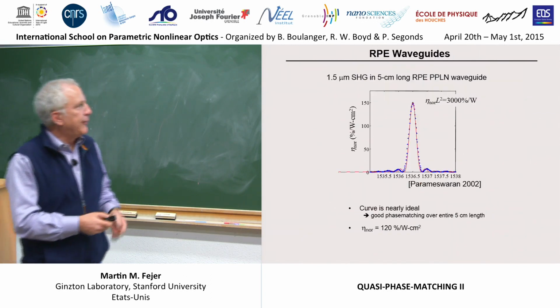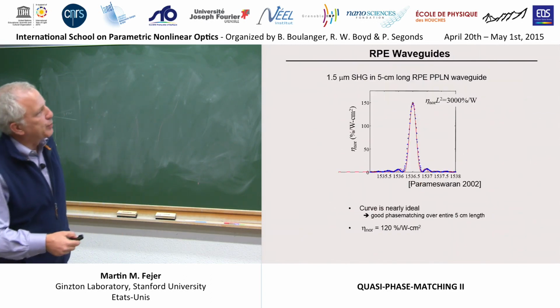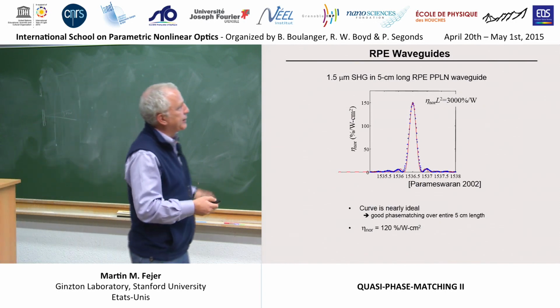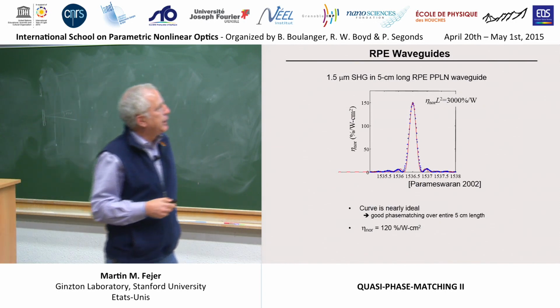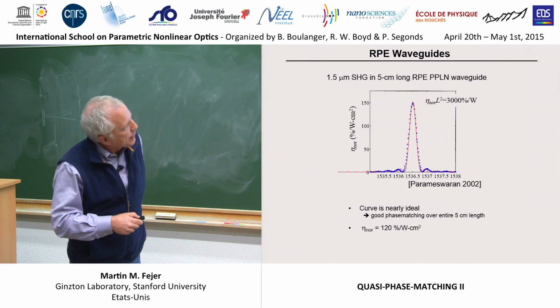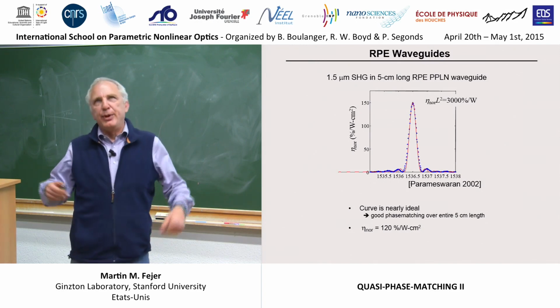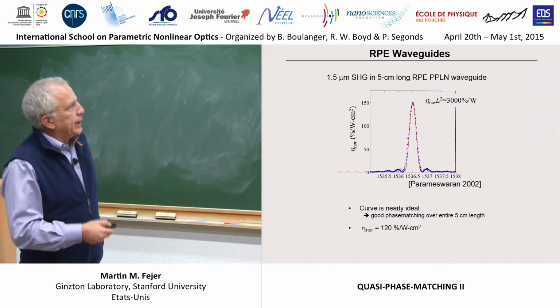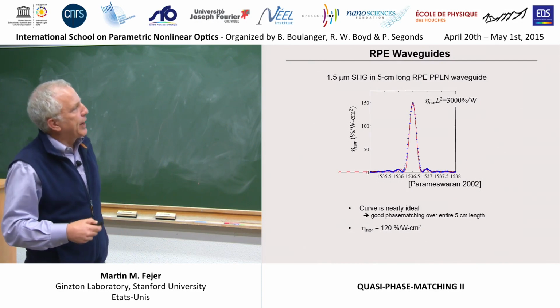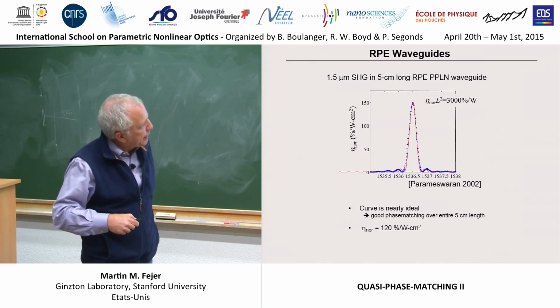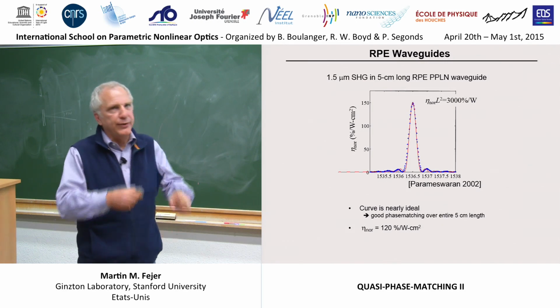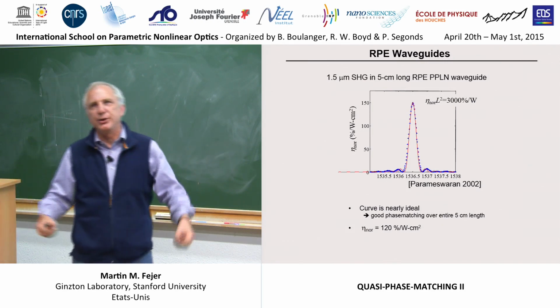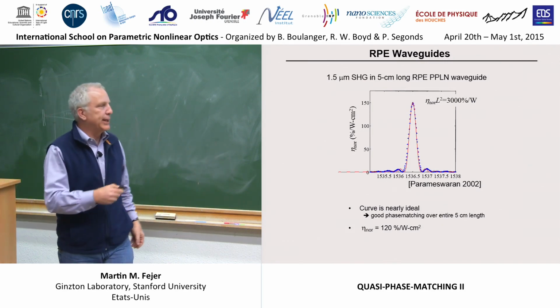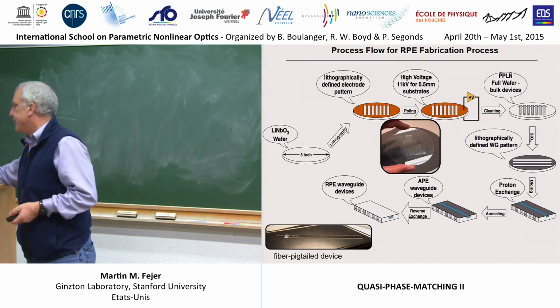This is a 5 centimeter long reverse proton exchange waveguide in lithium niobate, for harmonic generation of a 1.5 micron laser. You can see very high efficiencies, 3% per milliwatt - that's 3 or 4 orders of magnitude higher than in a bulk crystal. You also see a very clean sync curve, indicative that it's a very homogeneous structure. So it is possible to build waveguides that behave decently.